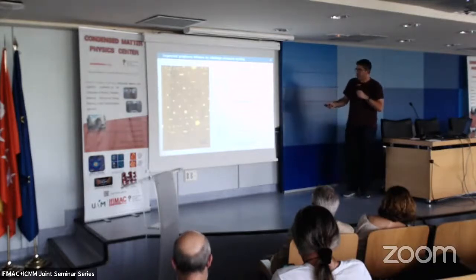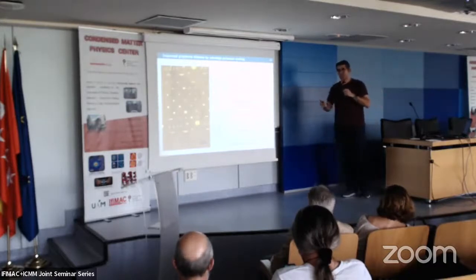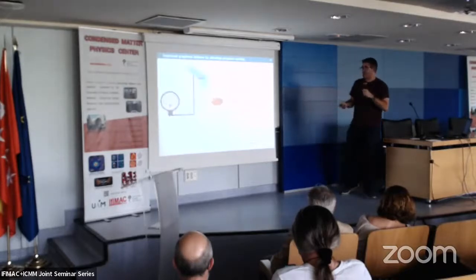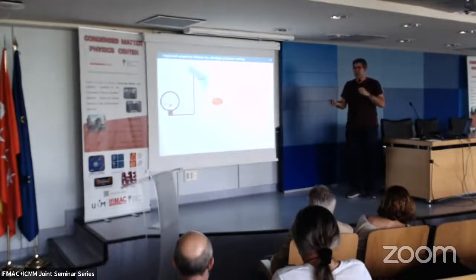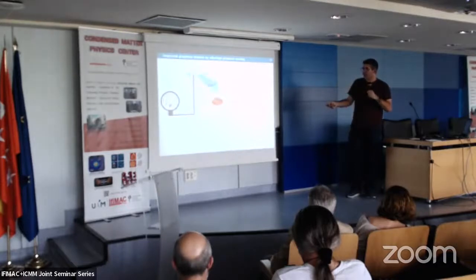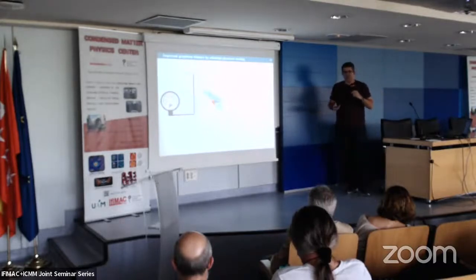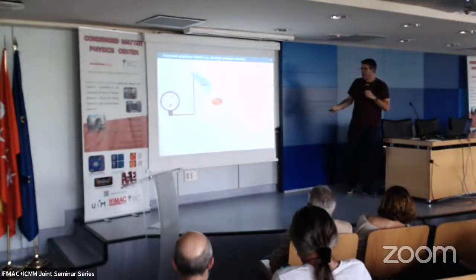And basically, from these results, I will not go in detail, but what we can infer is that the leakage was occurring mainly through the graphene substrate interface and not by diffusion. So in order to verify that, we came back to this ultra-high pressure approach, and we decided to study the same blisters before and after sealing, because if we just make something like this in the cartoon, in which we seal an area around the hole with this ultra-high pressure, we will increase the coupling between graphene and the substrate. So if the molecules are diffusing through the interface, the diffusion will be hampered, and in principle, times should increase. Okay, so we did that.